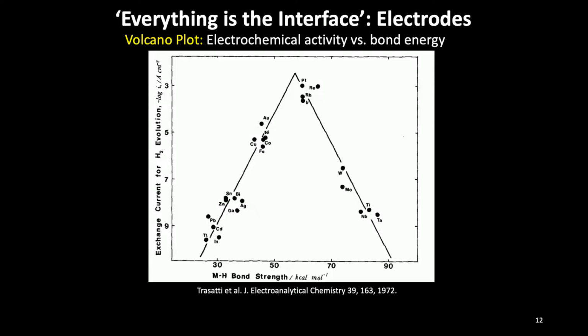This is looking at the exchange current at zero bias as a function of metal hydrogen bond or metal ion bond. And if we have a small bonding energy between the ion and the metal, which is the surface of the electrode, that means that ions in tissue will have small residence time on the contact and therefore have less chance to participate in a Faradaic reaction. If that bond energy is high, that means that the metal ion will have a long residence time. There is one Faradaic reaction, but you're blocking that adsorption site. So the sensitivity is low.